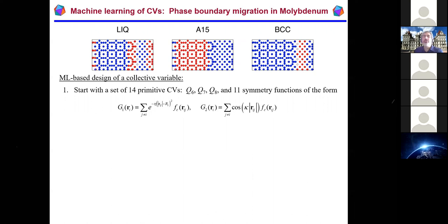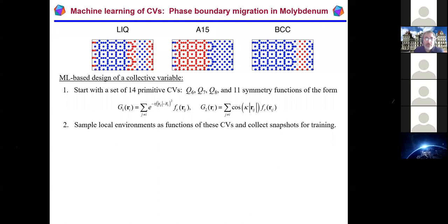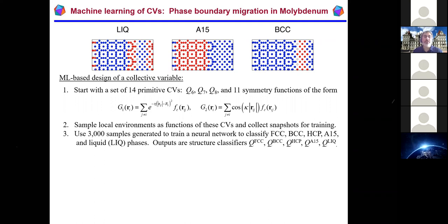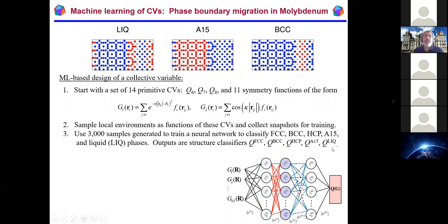What we do is sample local environments using these collective variables. We collect snapshots of these for training, and then we build a classification neural network that can tell us about the local environment, and therefore, when you sum over all the local environments, you get a global classifier of what kind of structure you actually have. Well, in molybdenum, you have a bunch of different possible phases: FCC, BCC, HCP, A15, and then what we generally call liquid or disordered phases. And so we have a classifier for each one of those. So you run different examples of MD in these different phases, plus some interface phases, and then you train your neural network to output a classifier vector for you.